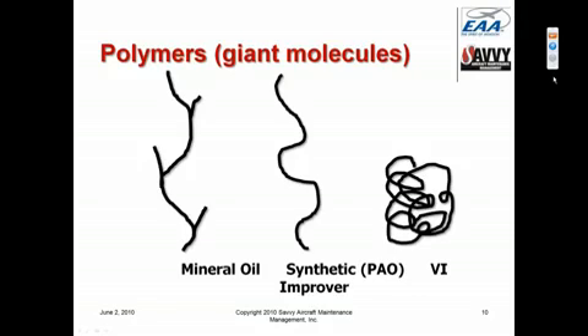That's not true of synthetics like PAO. And so, for example, in automotive use, synthetic oil can be left in service much longer, and the oil change interval can be extended because the synthetic oil doesn't degrade in viscosity as it remains in service. It can retain its viscosity characteristics for a very long time.